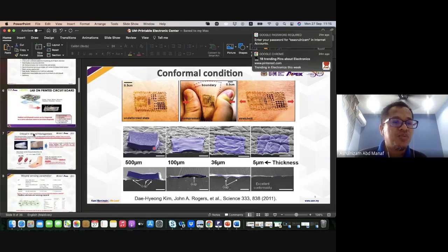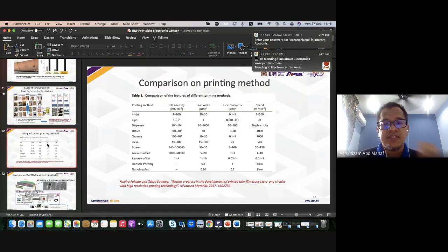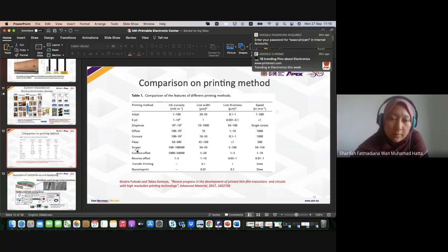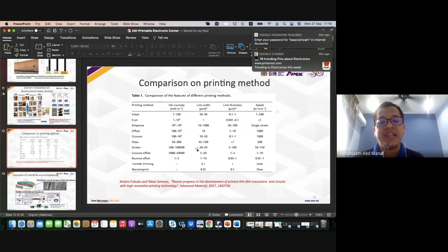But if you go through the papers from Someya, their ink with inkjet can reach a 30 to 50 micrometer line width, if you have the right ink optimal with the right printer. Screen print is like the maximum that can go, but you must ensure the right viscosity and the right cure temperatures with the printer that you have available in your lab. But inkjet gives the better resolution.